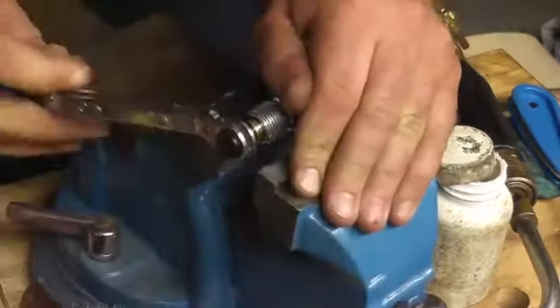Now when we heat this up, let me just tighten this vise. When we heat this up, the copper is able to conduct heat better than the steel. So the copper is actually going to wick away a lot of the heat, and the steel is going to get hot first. We want them to get hot at the same time, the same temperature, the same color cherry red around the same time. So what we want to do is concentrate our heat on the copper first until that just starts to turn cherry red, and then we'll move our torch down and put our heat on the steel, and that'll heat up right away and get nice and cherry red, and then we can touch the silver solder in.